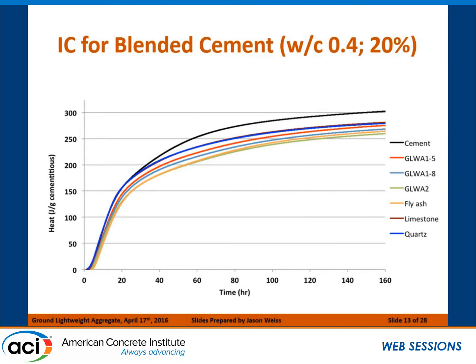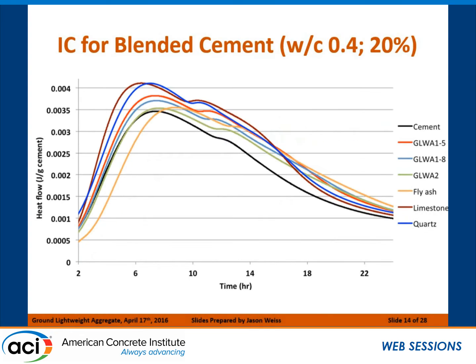They all kind of go high and to the right, like a good picture or something like that. But the basic idea is we're liberating more heat over time, but as I've said, we can't really distinguish what's going on in terms of the hydration of all these materials simply by looking at this graph. We can take the derivative of that and get the rate of heat release, and now all of a sudden we can see the same things that Scott was talking about earlier with accelerations that are happening when we get finer particles, but it really leaves us with an incomplete understanding of what's happening in the system.